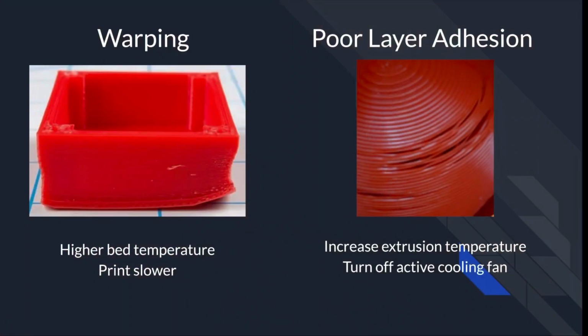There are so many things that can go wrong with a print. Two of the main ones are warping and poor layer adhesion. If you're experiencing warping, this is because of differential cooling. Some of your print is cooling faster than other parts. So one way to fix this is printing at a higher bed temperature, and another way to fix this is printing slower. If you're experiencing poor layer adhesion, this is again because your layers are cooling faster than other layers. So you can either increase the extrusion temperature, so the actual filament is hotter, being able to meld together better, or turn off the active cooling fan, so you're not cooling your print as you're trying to print.